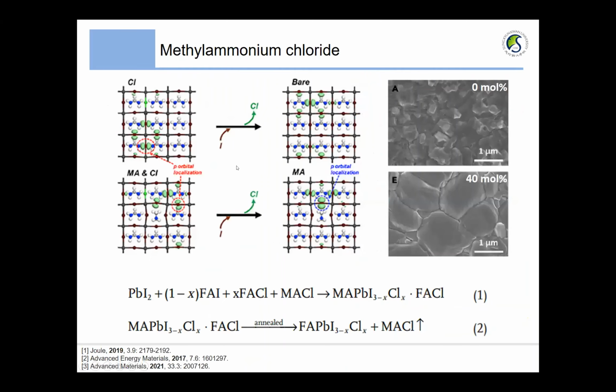Methylammonium chloride, or MACl, has been frequently reported to be an excellent stabilizer of the alpha phase FAPbI3, and most of the record-breaking power conversion efficiencies of FAPbI3 solar cells contain MACl additive in excess. The beneficial aspect of the MACl additive is that it can act as a stabilizer, where MACl can initially incorporate into the FAPbI3 lattice, reducing the lattice strain during the annealing process, and then MACl can be sublimated or evaporated during annealing and leave as a gas phase, which prevents unwanted bandgap widening or compositional changes of the FAPbI3.